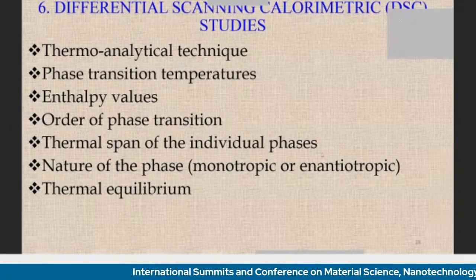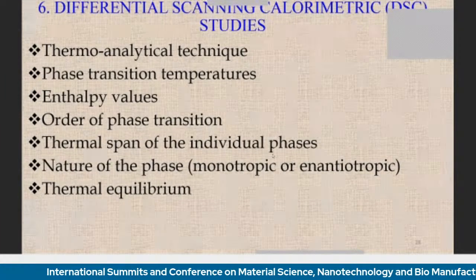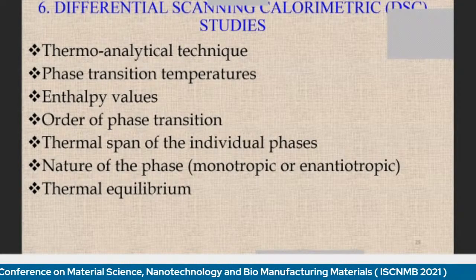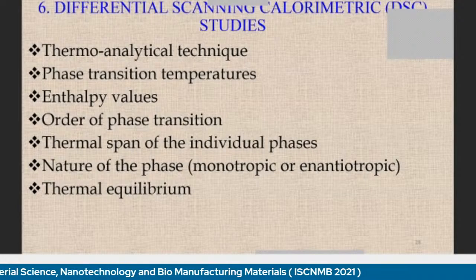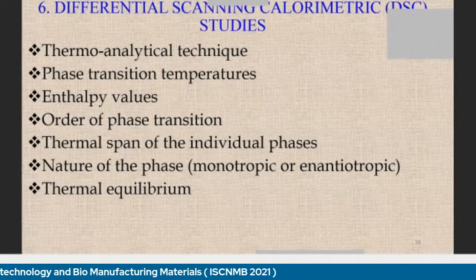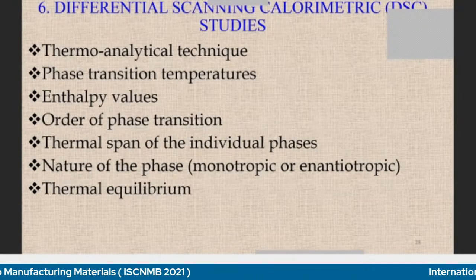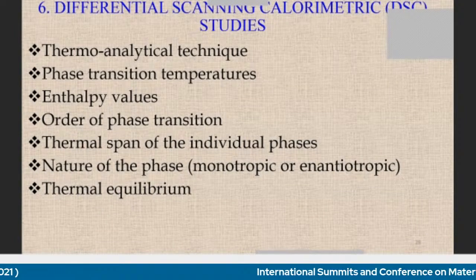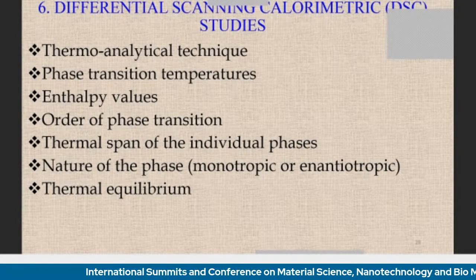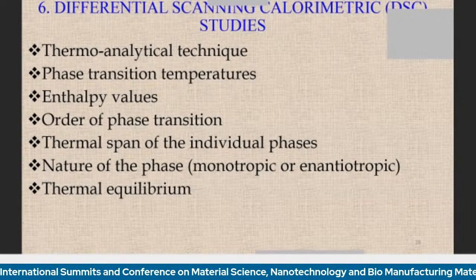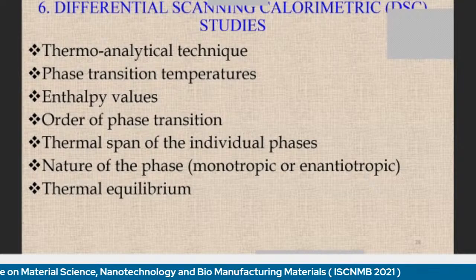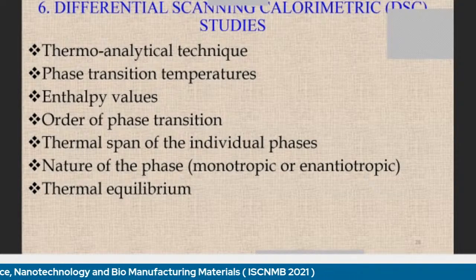So DSC, again, this is the thermal technique used for analyzing abundant information. From this DSC, differential scanning calorimetry, we could get the phase transition temperatures. We can correlate and compare the temperatures observed with POM and DSC. So DSC is a closed environment where we have different scan rates. We just purge nitrogen gas and we use it to maintain that stable environment. And there might be some temperature variation between POM and DSC. And obviously, we can confirm from the DSC